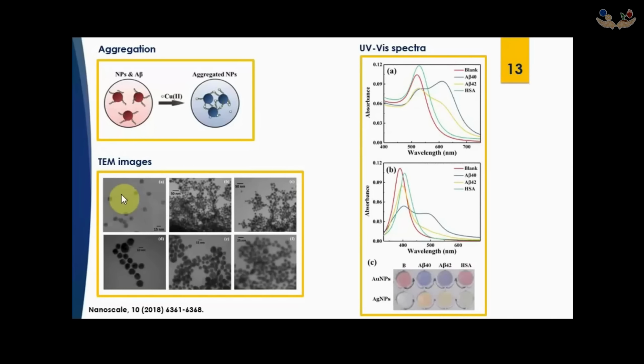TEM, transmission electron microscopy, images confirm that beta amyloid peptides cause the aggregation of nanoparticles. This image is the TEM image of gold nanoparticles. Then we add amyloid beta 40, and nanoparticles are getting aggregated. This one is for amyloid beta 42. This image shows the silver nanoparticles, and then we add amyloid beta 40 and amyloid beta 42. These images prove that the nanoparticles are aggregated because of the presence of amyloid beta and also copper ion.